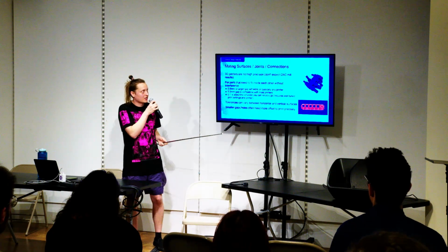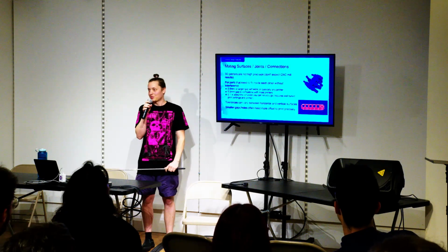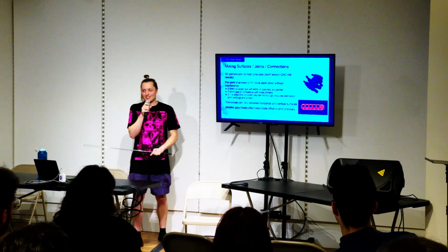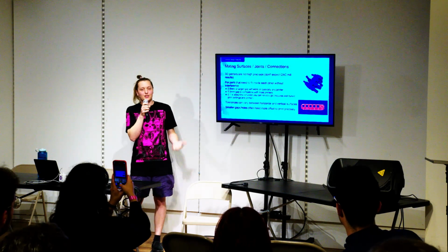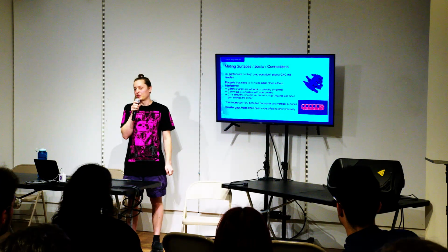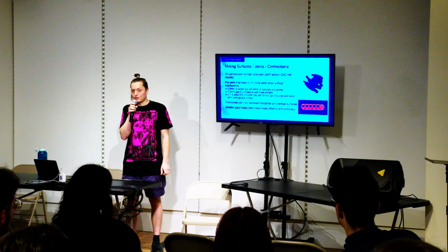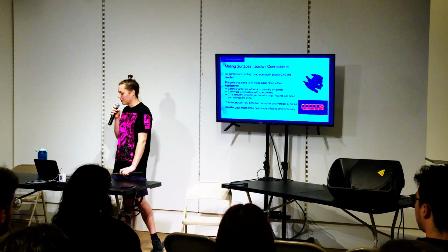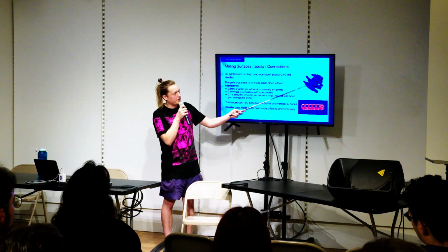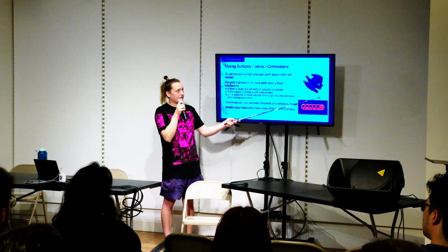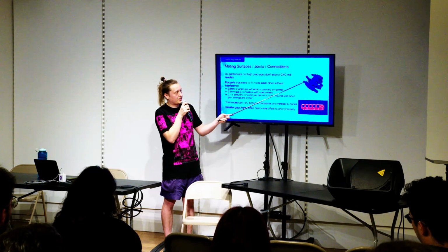Mating surfaces. One thing to watch out for is 3D printers are not super high precision. You shouldn't be expecting CNC mill type results. Reliably on printers, you can go about a 0.1 millimeter gap between pieces, and even that still usually requires a pretty well-tuned printer. So over here is an example of a test print that you can do. This prints all in one piece and has a slightly different size gap between each of these segments.